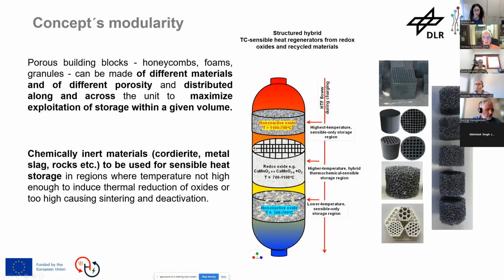Also to vary the porosity along and across the bed by artificial porosity along the periphery, and denser structures in the middle to level off the velocity of the air coming in, and also to combine different porous structures like honeycombs, foams, or 3D printed structures along this cascade. So one has many degrees of freedom to play, not only with the composition of the redox material itself, but also the structure, the porosity, and so on.